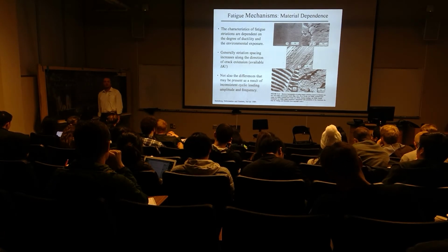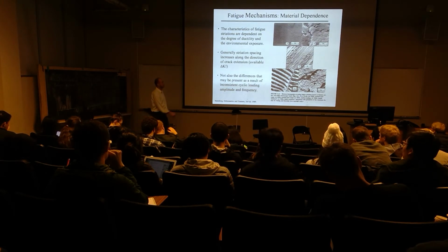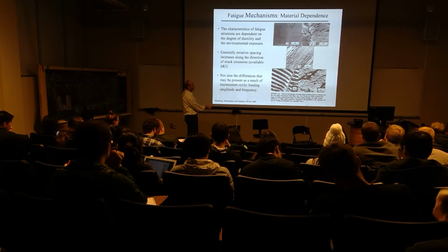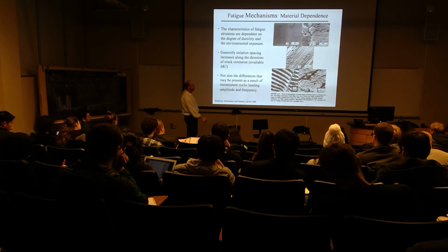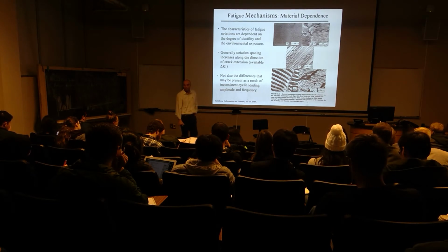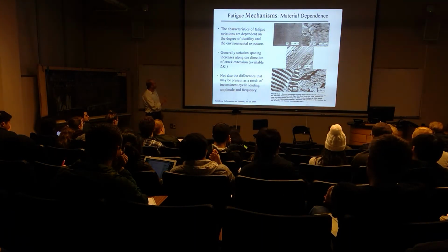just like that. And you can see those traces then on that particular specimen because they'll show you how long the crack wanted to go. We see TEMs of ductile striations, very deep and dark striations, differences that are caused by TEM. And then something with not quite as much ductility at all, brittle striations, so you can just barely make them out. Brittle, meaning that we don't have enough ductility to leave the signature of the crack. Okay? Do we have anything else here?